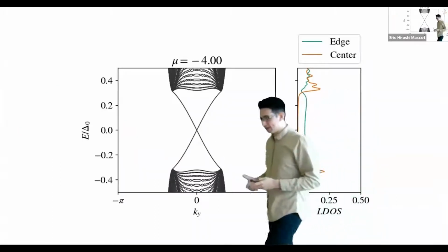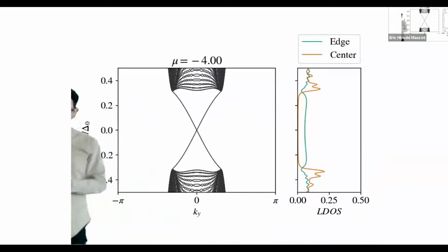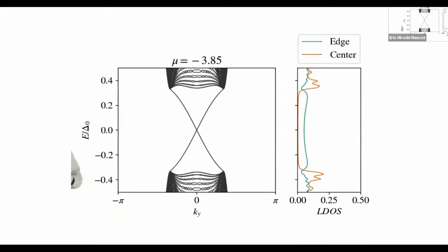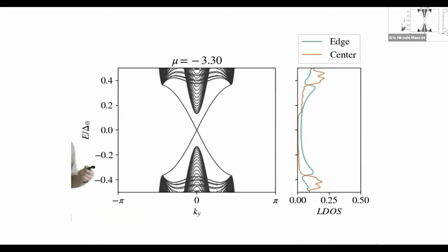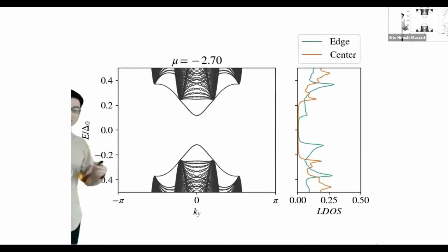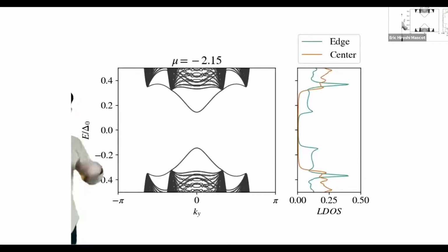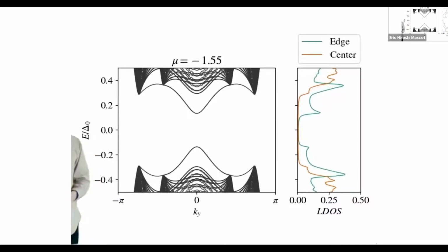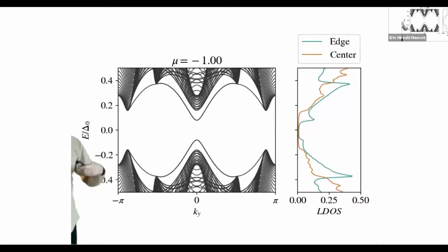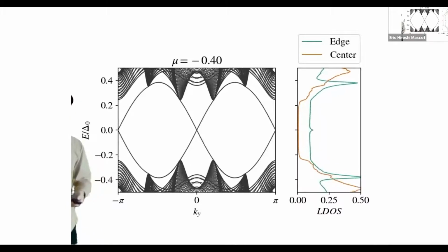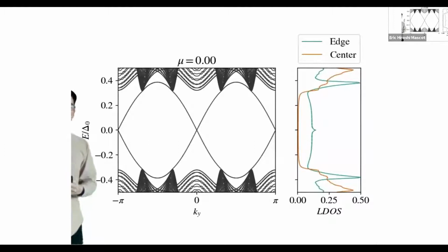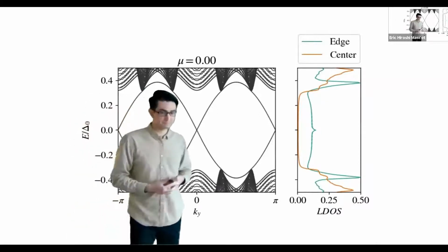So what happens in a phase transition? So we can change the chemical potential to go to different topological phases. And so as I change the chemical potential, eventually we close the bulk energy gap, and we still have these edge bands, but these are trivial. They do not cross the superconducting gap. And if we keep on going, we again close the superconducting bulk energy gap, and now we have two edge bands. And this comes from, again, the bulk boundary correspondence, where the Chern number is 2, so we have two edge bands now.